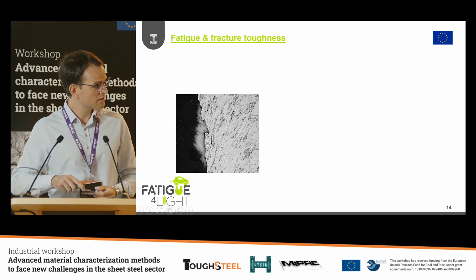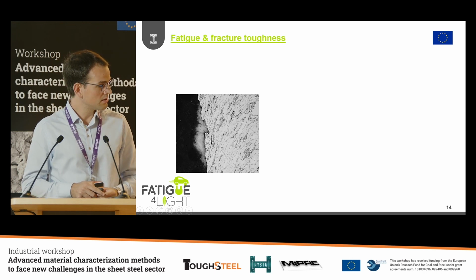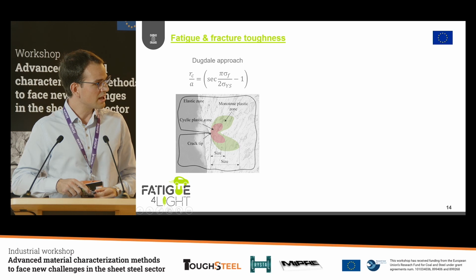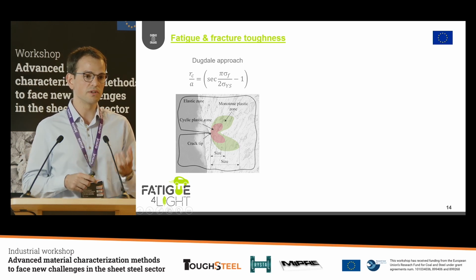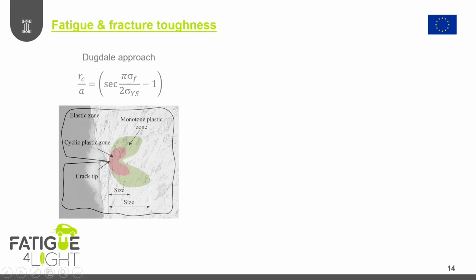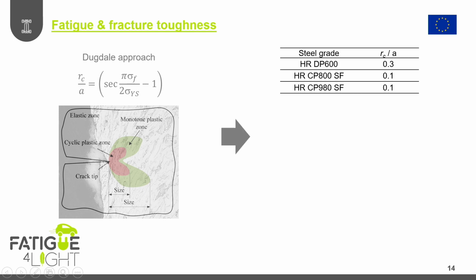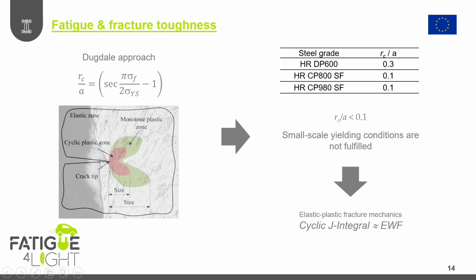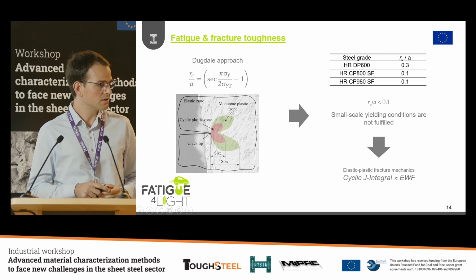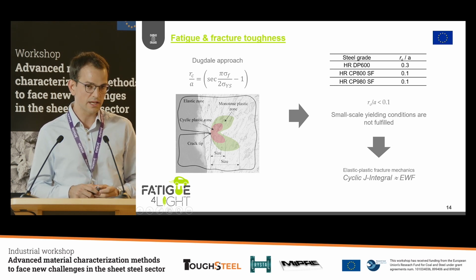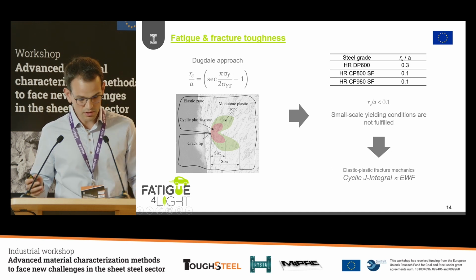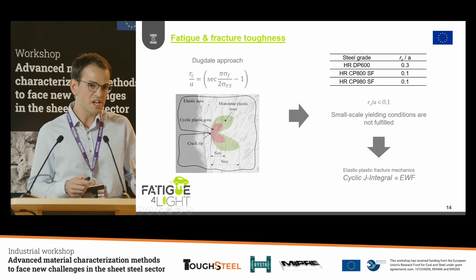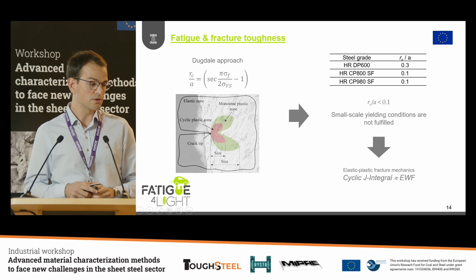Well, here you have a defect that we can find in the trimmed edge. And the main point is that if we analyze the dimension of the cyclic plastic zone at the tip of this defect, which can be considered as a crack, this plastic zone is quite large, so it is really relevant compared to the dimension of the crack. So for these materials, we can say that the small scale yielding conditions are not fulfilled. And if we want to explain how these small cracks behave in these materials, we have to use an elastic plastic fracture mechanics approach, where one of the most common and most used is the J integral, which is essentially equivalent to the essential work of fracture method.